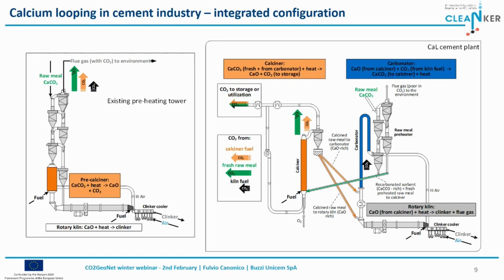So the emission of the calciner will be pure CO2, because we will not use any more fresh air here, but only pure oxygen. The calcium oxide produced in the calciner will be able to capture the CO2 emitted by the kiln, okay? And so out of the carbonator we will have no CO2, because the CO2 will be completely removed by the calcium oxide, and the calcium oxide will form calcium carbonate and will go again in the loop.